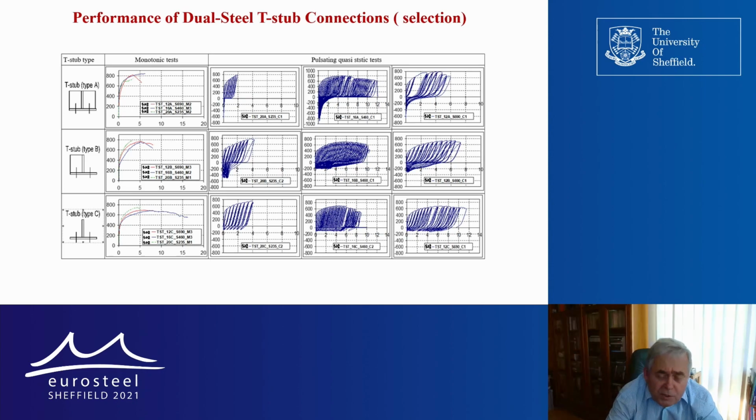What is important to see is that in this case 460 steel has a very good behavior, and I would say 690 is also acceptable. So the previous observations and conclusions for tests on material only are also confirmed in this case.